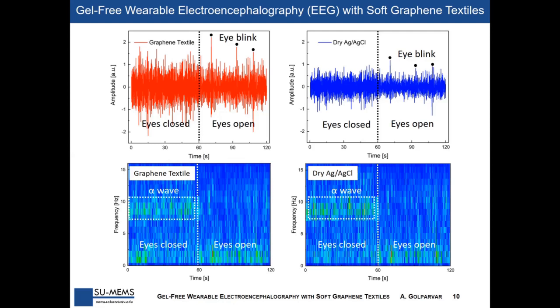For checking the functionality of the fabricated textile electrodes in neural biopotential monitoring, we benchmarked the EEG recordings using our graphene textile electrodes and the gold standard wet silver chloride electrodes. In this trial, the participant was requested to close his eyes for 1 minute and then open and read a text that appeared on a display. The figure above illustrates the acquired EEG signals after signal conditioning, and the correlation coefficient between these two recordings was calculated to be 91% during the entire 2 minutes of the experiment.